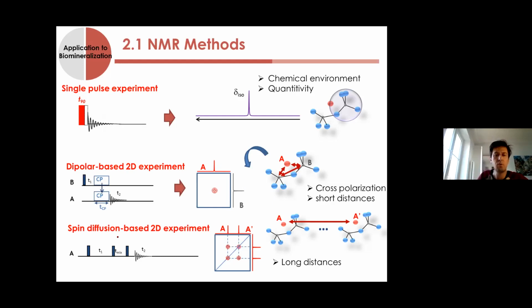Then you can have access also to longer distances when you are using techniques that are based on the use of spin diffusion. The mechanism is a little bit different, but basically you can see the correlation between one given nuclei, one given group, but with some diffusion of the magnetization along the space. And it works well with long distances, meaning more than 10 angstroms, let's say.